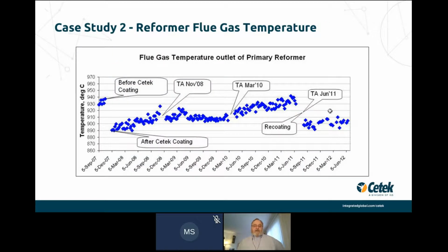Now this is the chart that shows the flue gas temperature outlet in degrees centigrade. I'm looking here. This is when we applied the coating in 2007. The flue gas temperature started off at about 940, 935, but dropped significantly to around 890. But then in use, it started to creep up. There was a turnaround in 2008. After that, things stabilized, and after the turnaround in 2010, the flue gas temperature started to increase again. And in 2011, they went down and we recoated the unit, or touched up the unit. And then it was up until 2012, which is all the numbers I have, the performance was fairly stable.